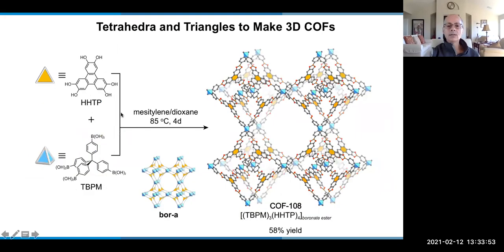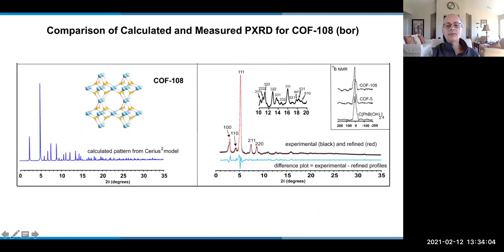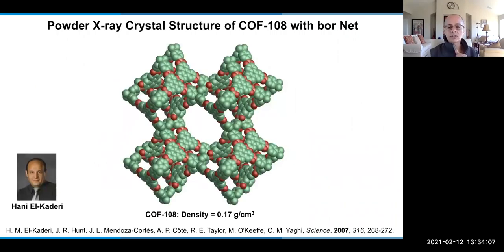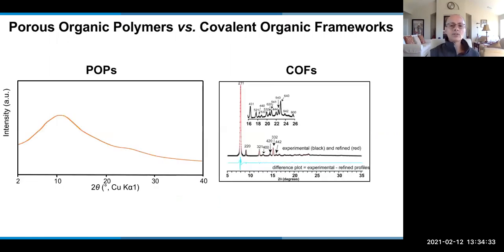We can characterize it using, again, the same conditions, but different building units. We can make the other topology, the BOR topology. This is the X-ray powder diffraction of the BOR topology, and this is the crystal structure using powder diffraction of this BOR COF we call COF-108, which is a 3-dimensional COF, and it's the least dense crystalline solid known at room temperature, aside from lithium. This is one of the lowest density materials known. So this brings me to a point that I want to try to make, is that COFs are crystalline, as you can see here from the X-ray powder diffraction I'm showing on the right.